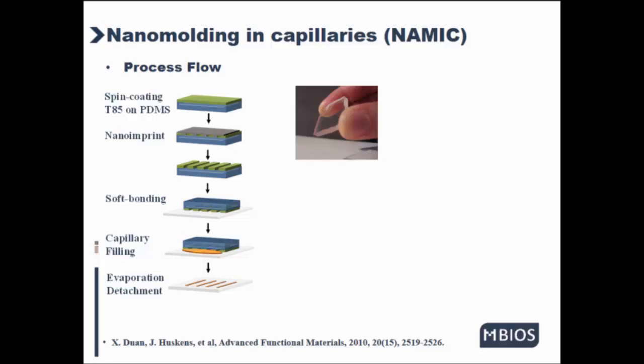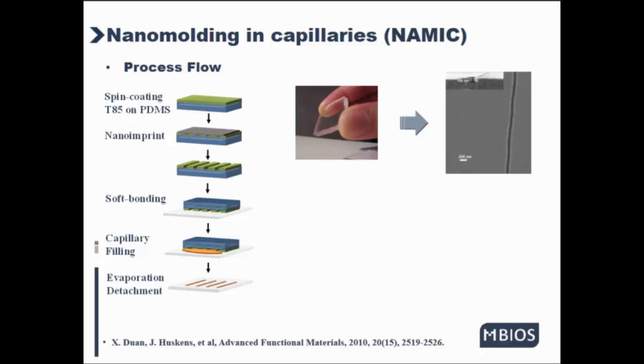First, a thin film of imprint resist T85 was coated onto the PDMS substrate. After that, the composite PDMS substrate coated with T85 and the silicon template were inserted into the stamping machine. After the nanoimprint process, nanogrooves were formed on the PDMS substrate. And this picture shows the SEM results of the nanogrooves fabricated on the PDMS substrate, with the cross-section of the imprinted